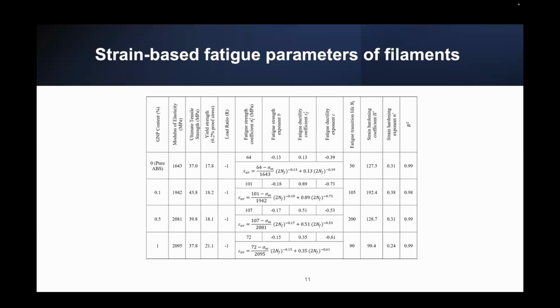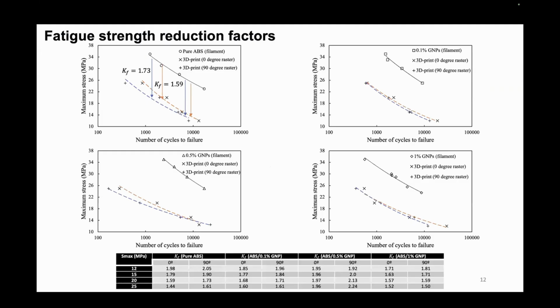We have used these data along with the Ramberg-Osgood and Neuber equation to obtain fatigue strength reduction factors. And all these data have been used to predict the fatigue life. So here we can see that the fatigue life of filaments is much higher than fatigue life of 3D printed samples. That's why we have considered that the 3D printed sample can be considered as a homogeneous material, but with a notch. So we have calculated the notch strength reduction factors for all these load levels, and the results have been summarized in this table.